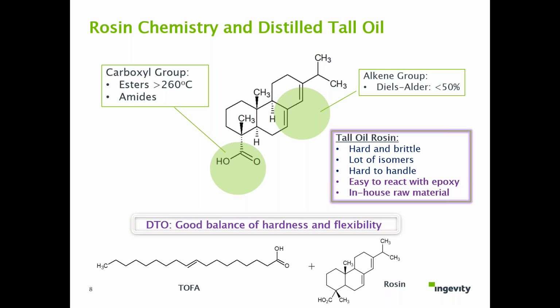Another site you can see is the conjugated double bonds, which can go through a Diels-Alder reaction with fumaric or maleic to introduce additional functionalities. But they only make up to 50% of the rosin composition. So overall, tall oil rosin is a hard and brittle material. There are a number of isomers, and it is hard to handle because it is a room temperature solid.